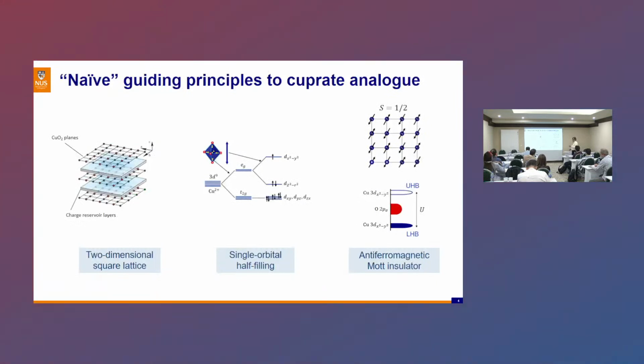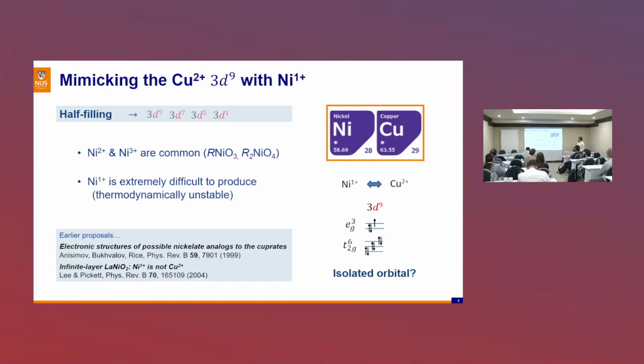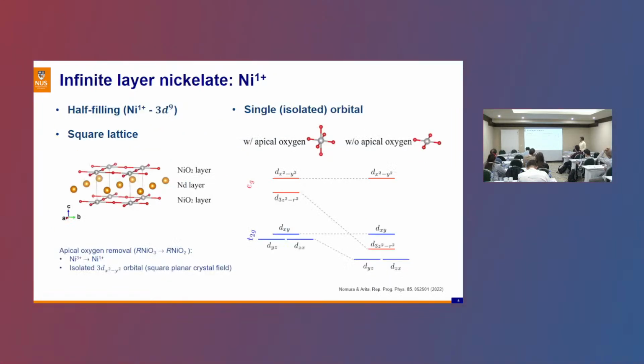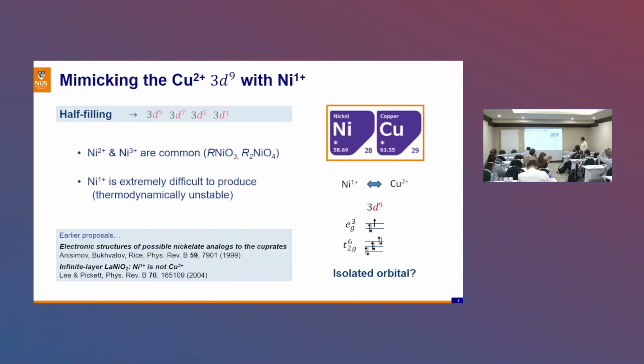As a guiding principle, and naively, we can think about this square lattice of the cuprate as a starting point. Then we have this two-dimensional nature with a single orbital half filling, and then, of course, the antiferromagnetic ground state. Looking into all this, nickelate has been proposed to be a promising system because, in principle, to get the half filling, you can do different orbitals, 3d7, 3d5, 3d1, but nickelate promises to have this 3d9 if you can make it nickel 1+. This is not a stable system, so naturally you will get 2+ or 3+. To be able to produce the nickel 1+, you have to remove the apical oxygens in the perovskite structures.